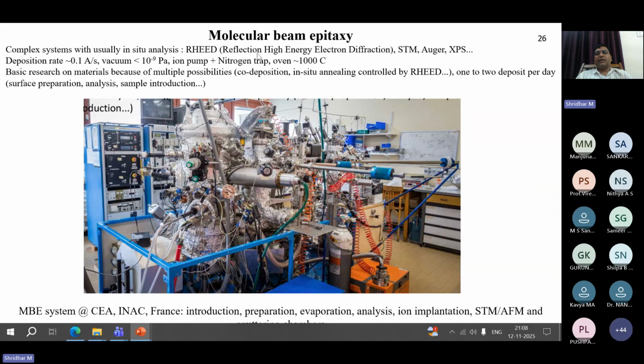Now, molecular beam epitaxy, here you can see, is also a complex system where you need reflection high-energy electron diffraction, scanning tunneling microscope, Auger, and XPS. Deposition rate is 0.1 angstrom per second, and vacuum is 10 to the minus 9 Pascal. It has an ion pump, nitrogen trap, and an oven of 1000 degrees Celsius. It is used for basic research on materials because of multiple possibilities: co-deposition, in situ annealing controlled by RHEED, one to two deposits per day, surface preparation, analysis, and sample introduction.